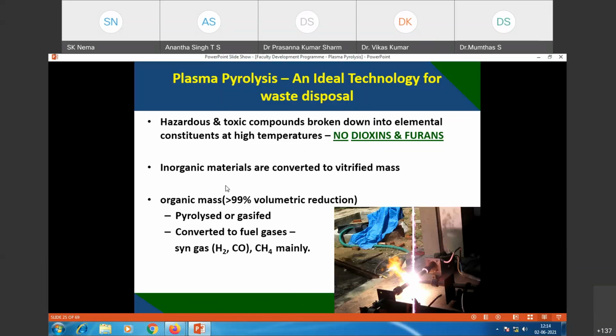And inorganic materials are converted to vitrified mass. You can maintain the temperature in the range of 1500 or 1600 degrees centigrade in the reactor, and you can vitrify the inorganic material into the lump, so that the leaching can be avoided. Because if the fine particles of metals are there, with the rainwater they go inside the ground. They mix with the groundwater and can pollute the groundwater.